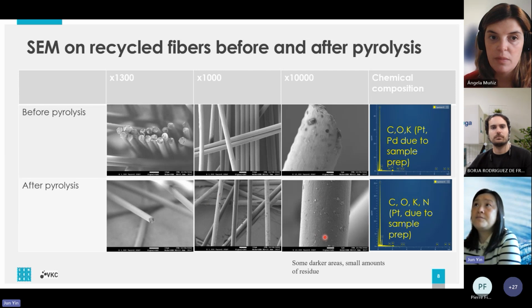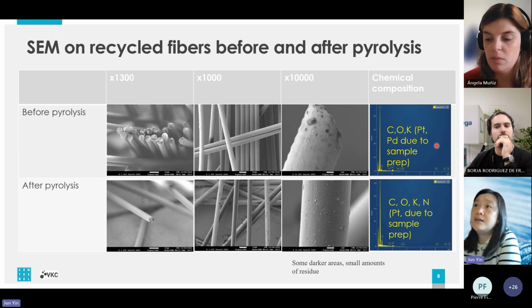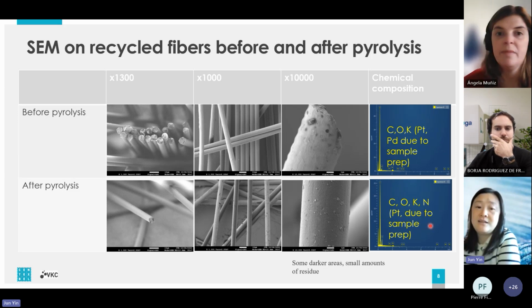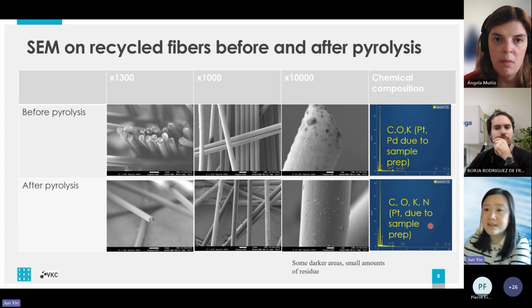And also by comparing the chemical composition, we can see on the original virgin fiber, we have carbon, oxygen, and potassium, but after pyrolysis, we can see nitrogen on the fiber surface, which is due to the process of pyrolysis.